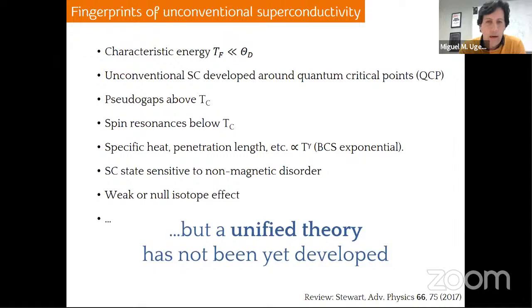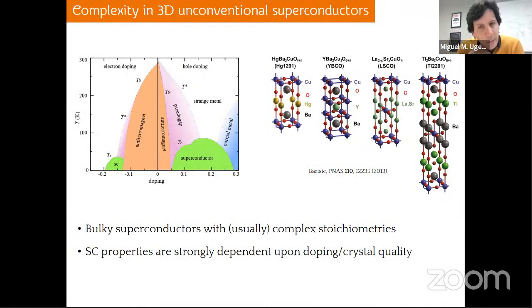So it's quite hard to study unconventional superconductivity, and one of the reasons, that's my personal opinion, is that there is a high complexity associated with the study of bulk unconventional superconductors, because these materials in general show a very complex phase diagram. I show you here one of the examples. So the superconductivity is constantly surrounded by many-body phases, and this phase diagram is highly dependent on the exact amount, for example, of doping in the case of cuprates, or pressure, strain, etc. And that makes it quite challenging to study these materials both from the theoretical point of view, but also from the experimental point of view.